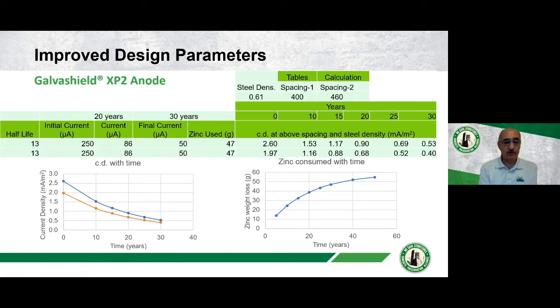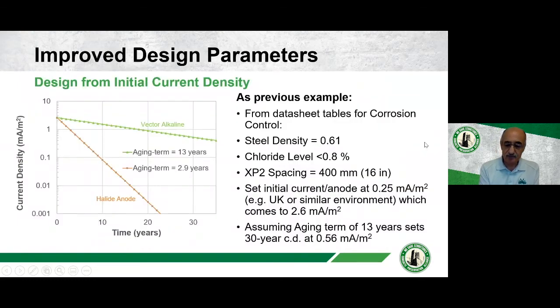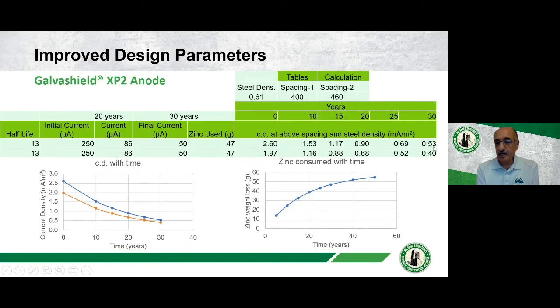The same anode will produce 500 microamps. But on this occasion, I'm assuming 250 because it's UK conditions. The spacing we got from the data sheet, it's 400. Steel density is 0.61. We can then work out the current density that we are producing, which is 2.6 for the steel. And that diminishes, half-life tells us that diminishes with time, and we end up at 30 years, 0.53 milliamps per meter squared.